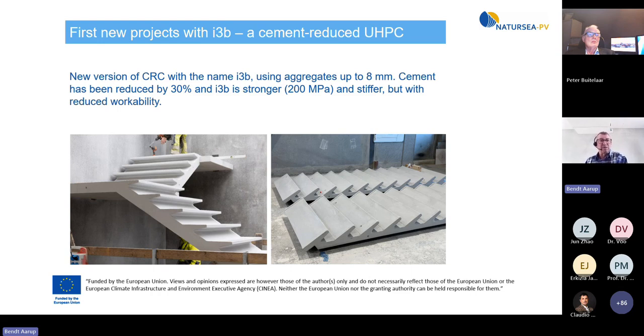And these are some examples of the new types of staircases, standard staircases that we're doing with this mix. We call it I3B, and this is because the concrete that we used prior to this was called I2, and the B is because we use a little bit of bauxite sand to have a stiffer and stronger mix, which means we can reduce the thickness of staircases and balconies even more, and have less carbon footprint that way.